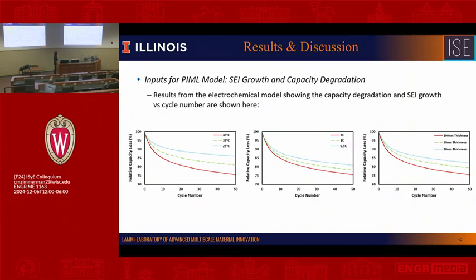So the degradation process, one of the parameters we use to quantify the degradation is relative capacity loss. So it always starts with 100 and changes over the cycle lifetime. Here, those are the major parameters we're including in our multi-scale simulation. We can do sensitivity studies to look at how those different factors, either from the design of the anode or the operation conditions of the anode, collectively impact the lifetime of the 3D architectured silicon anode.